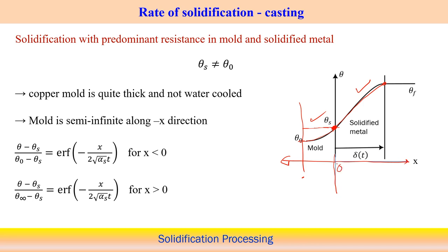We can see that (theta minus theta s) by (theta 0 minus theta s) equals the error function of x by twice root of alpha s t, for x less than 0, and in the other case it is for x greater than 0. Here you can see this is theta 0 and this is theta infinity also. In these two cases the temperature distribution